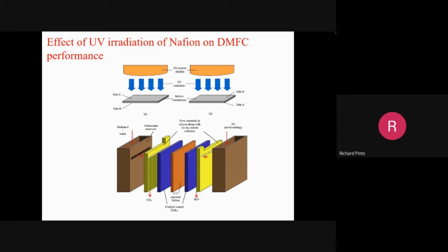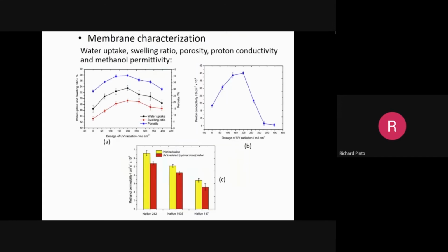The schematic is shown here, and it is exposed on both sides because H plus hydrogen ions have to move through the membrane. Then we have, again, the exploded view shown here. You have the membrane here, exposed on both sides, and you have the UV ray exposed membrane. This is the way it is assembled, and this is the schematic of exposure. And this is the lamp from the mask aligner. Now, what is the effect? The effect is very, very significant.